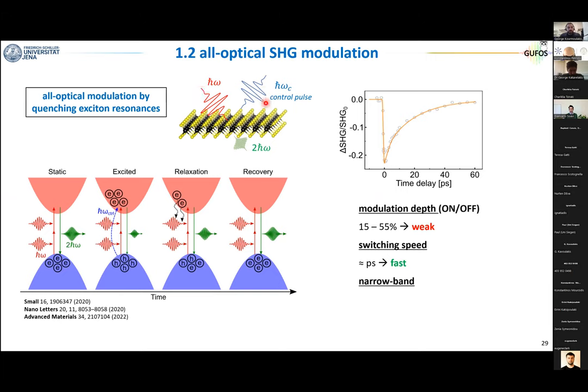That is, you modulate the efficiency with an optical pulse. You see this graph reminds what I showed before about graphene. The time delay is the delay between the control pulse and the fundamental. Here, they're modulating the second harmonic in TMDs. You see now the dynamics are a bit slower. They are tens of picoseconds. And the idea is that the second harmonic must be resonant with the band-to-band transition, so with the exciton of TMDs. The control pulse generates electron holes in the valence and conduction bands. And as you generate these new electron holes, you reduce, let's say, the strength of your optical transitions, and the second harmonic will be quenched. So now the advantage is that the speed is much higher. The disadvantage is that the modulation depth is lower.